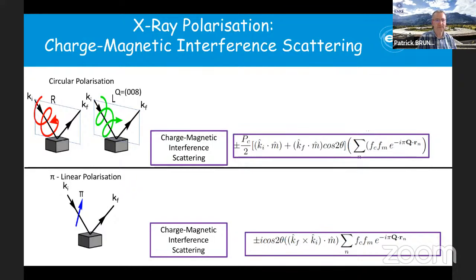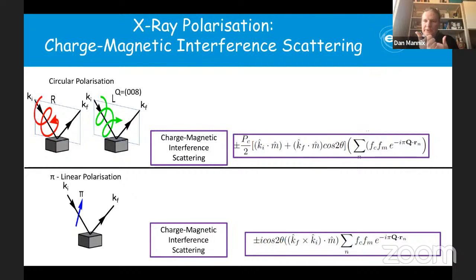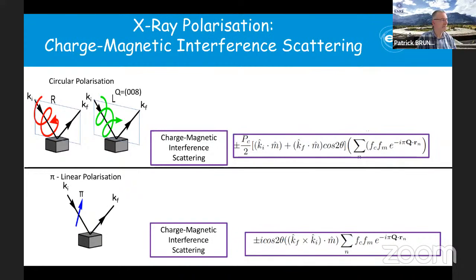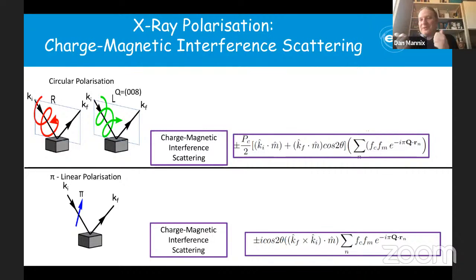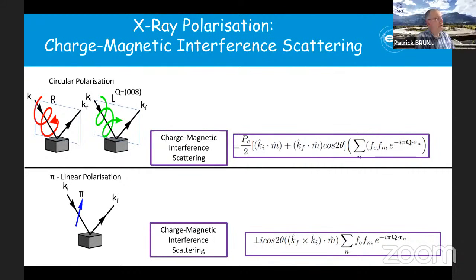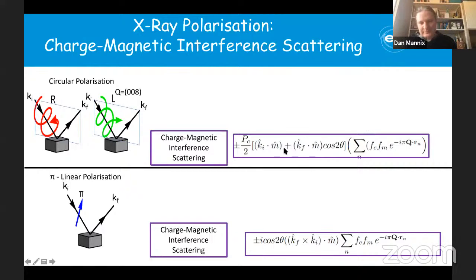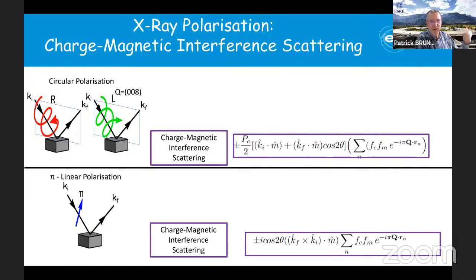You can't tell a difference when you do the cross product, between the one sticking out of the scattering plane in one direction and out of the scattering plane in the other direction, like this. If my nose is actually the beam direction, then you can't tell the difference. Okay, if I see the formula on the upper half of the slide, you project M on a linear combination of Ki and Kf. Yes, along with a projection term. So depending on how you are with respect to that, you can see or not see the contrast.